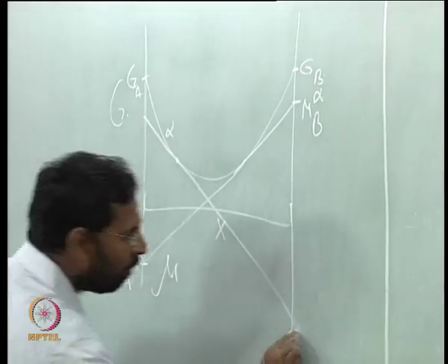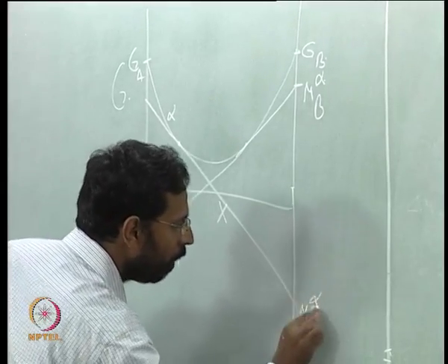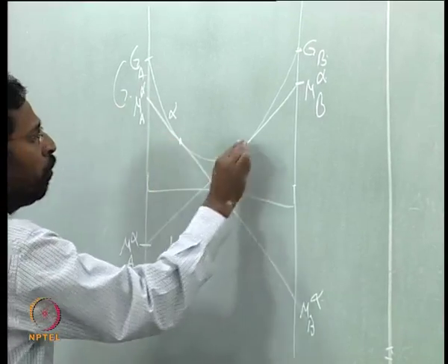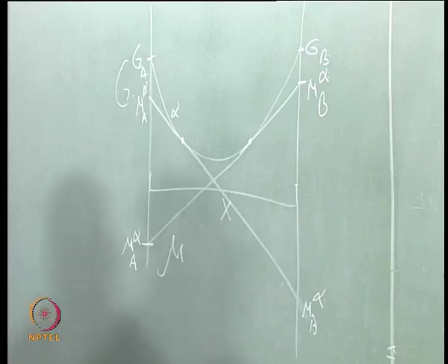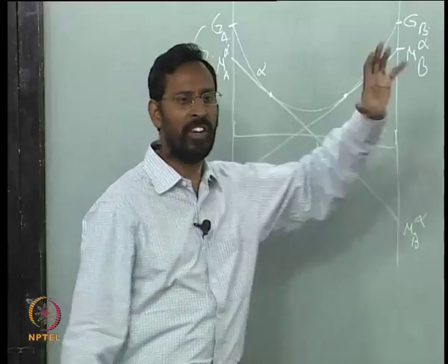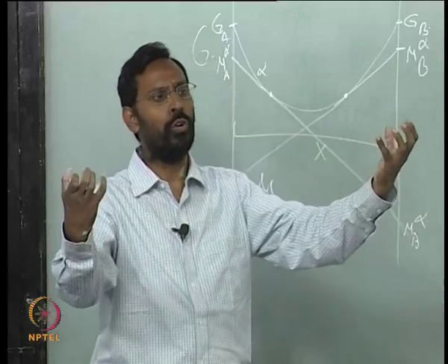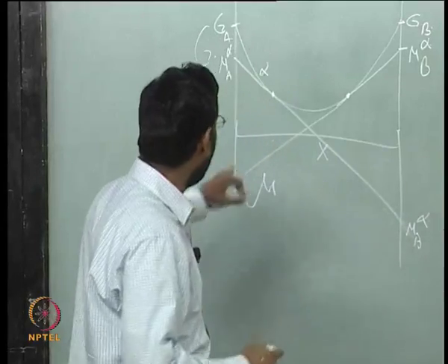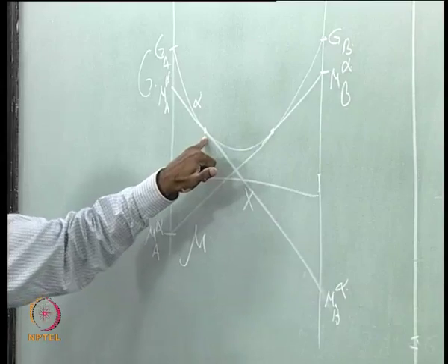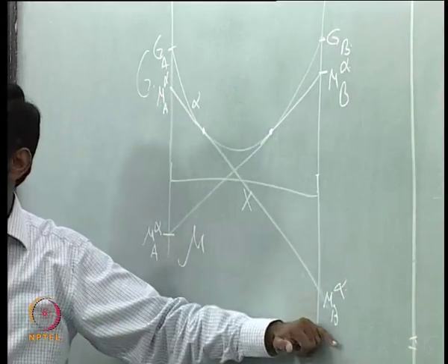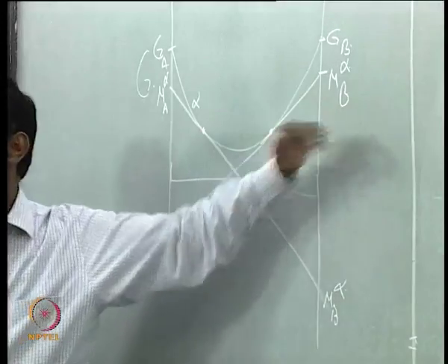You would see that this is mu B in alpha, this is mu A in alpha. That means for these two compositions, if I take alpha of, let us say, 30% B and alpha of 70% B, you would see the alpha on this side would have higher activity for pure A when compared to B, and on this side higher activity for pure B.